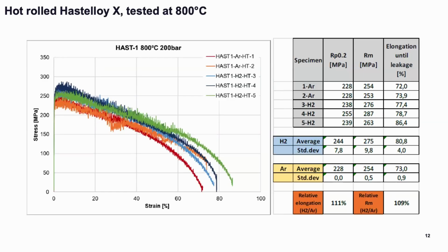So if we go to the high temperature testing, then for the hot rolled Hastelloy X material at 800 degrees and slow strain rate, we obviously have a very large creep influence, so much lower strength, but we do have a very large elongation to fracture. In this case it's actually higher in hydrogen than in argon, but I think that is mostly reflecting the scatter of the testing more than anything else.